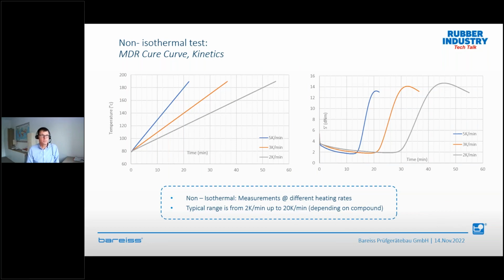The second one I wanted to show, because in the rubber industry the processes are not isothermal, they are always non-isothermal. So let's run some non-isothermal curves on an RPA or on an MDR. We can run with, for example, 2, 3, 5, 10, 20 Kelvin per minute. Here is an example from 80 degrees up to 200 degrees.